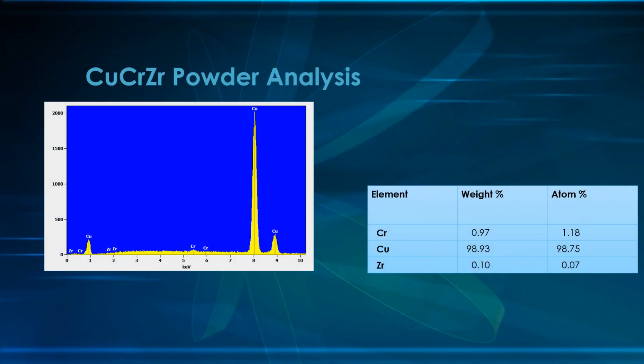Here you can see the EDS analysis made on the powders. So you can see that those powders contain about 1% of chromium and 0.1% of zirconium. So we verified that the composition of the powders is the nominal one.